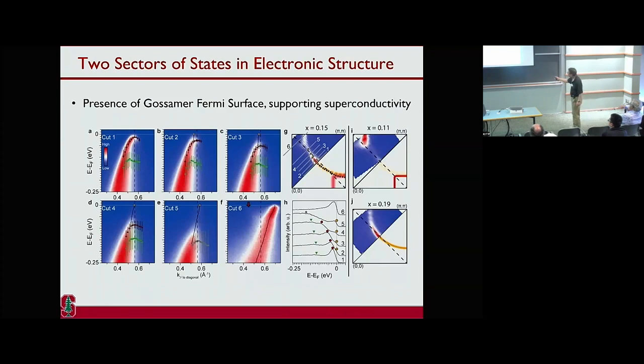So the proposal will be, say, that's the map of the Fermi surface, and you can say that there are two pieces. There's a reconstructed Fermi surface, the larger piece, with a larger gap, this large gap. Then there is a ghost-like Fermi surface. That's why we call it the Gossamer, stealing the words from others. And you can see that, of course, at a higher doping, the physics goes away. And that's where the superconductivity comes in.